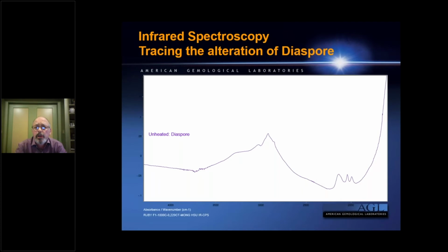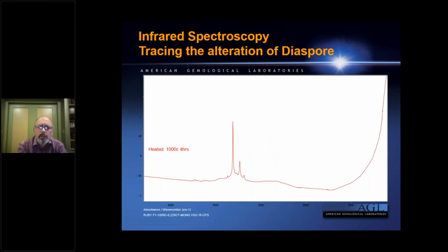When we start to talk about infrared spectroscopy, this was a Mong Hsu ruby. It had inclusions of diaspore, which we were able to recognize. Again, I showed this and published this in 1995. We're seeing that even with relatively low temperature heating, the diaspore goes through a process of dehydroxylation already at about 450 degrees centigrade.